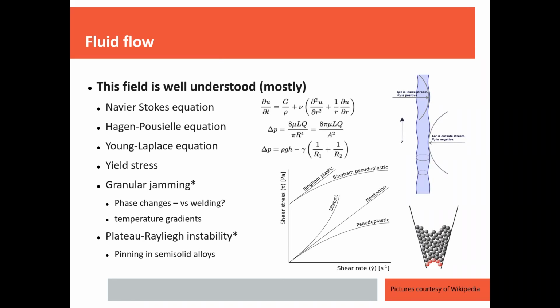And that is not particularly studied, but it's very interesting for applications because I was able to extrude in early tests like 20 centimeters, 30 centimeters of wire without anything relieving the strain in the wire. So that's a heavy weight to fight against with the plateau Rayleigh instability. So it was surprising that we were able to get that much wire without pinch off.